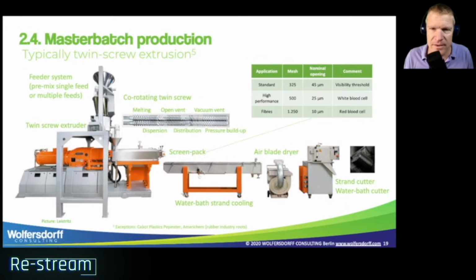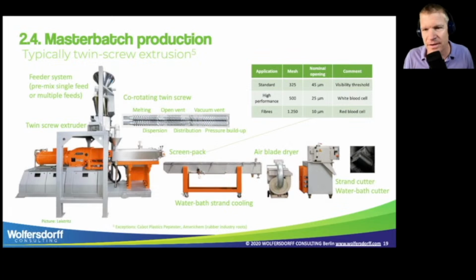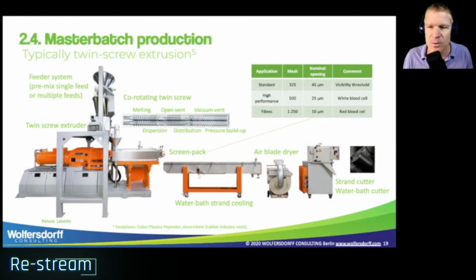Then we might have a screen pack, which is like a sieve pack, which is straining for oversized particles. And the oversized particles could be really varying depending on the pigment. Generally, for standard plastics, we might use a 45 micron screen, which is screening everything above 45 micron. For high performance plastics, we might use 25 micron. This is already getting into the application of polypropylene fibers, for example. And this is the size of a white blood cell, so very, very small. Synthetic fibers might even require 10 micron screening, which is the size of a red blood cell, very, very small.